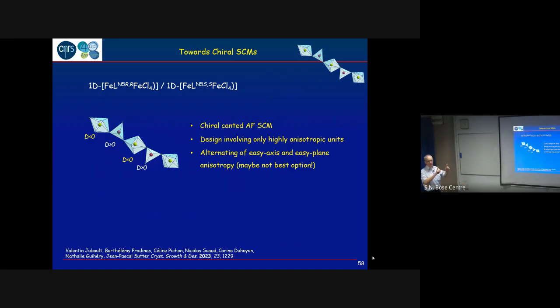So it's because we have an anisotropy, and this anisotropy is not aligned. If it were aligned, you would cancel the local moment. And if you don't cancel, it means that there is a continuum. And this is why we see this. But you're right, we should do a neutron experiment. We are not used to these experiments, but this would be a good way to prove it. But just the magnetic behavior tells you that you have